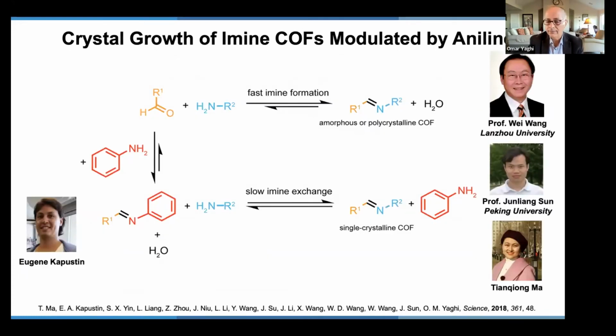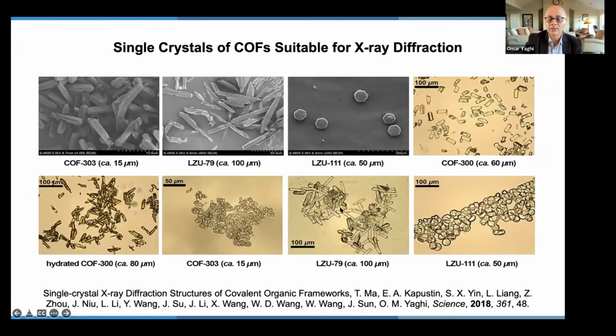And I just want to say that furthermore, we can characterize these by single crystal X-ray diffraction, which we developed in a collaborative project with Wei Wang's group in Lanzhou University. We developed methods using modulators like aniline to produce single crystals of COFs. These are crystals that molecular chemists are used to making. Now we are making them for extended structures that are linked by strong bonds. This is really a dream come true for chemists, and it allows us to characterize COFs with the same accuracy as you would characterize molecules.